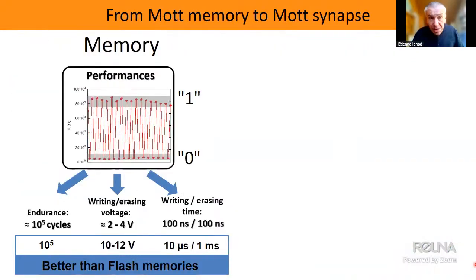All right. Just in terms of performance, the endurance of this memory is quite good. We can cycle over more than 10 to the 5 cycles. Also, the writing and erasing voltage is quite low, in the 2 to 4 volts range. As a comparison, for the flash memories that you use in your computer or your cell phone, the amplitude of the pulse is much higher, around 10 to 12 volts, just to write or erase an information in the memory of your cell phone. And also the writing and erasing time, I already mentioned that, is typically of the order of 100 nanoseconds, but we can even go lower. And once again, it's much shorter than what happens in flash memories.